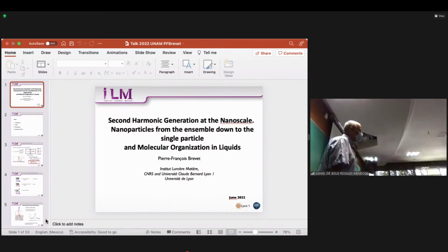What I was saying to Alejandro earlier on is that tiny particles will, let's take gold, have the interband transition, then the very nice surface plasmon, and then it vanishes at longer wavelength. This is the surface plasmon, called the dipolar surface plasmon, for gold around 520 nanometers. Then we have a response there.